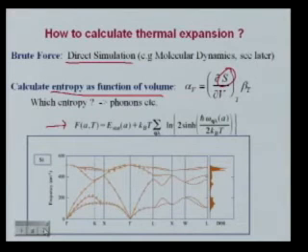It's typically done either by linear response techniques, where you perturb a lattice literally by a phonon with short wavelength so that you can calculate the energy of it. So it's literally like setting up a supercell with a phonon in it. It's called a frozen phonon approximation. There are perturbation techniques, linear response techniques, and then some people do it in real space by calculating force constants and setting up force constant models for phonons.